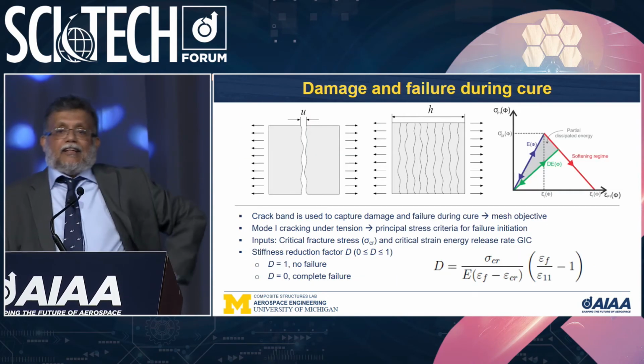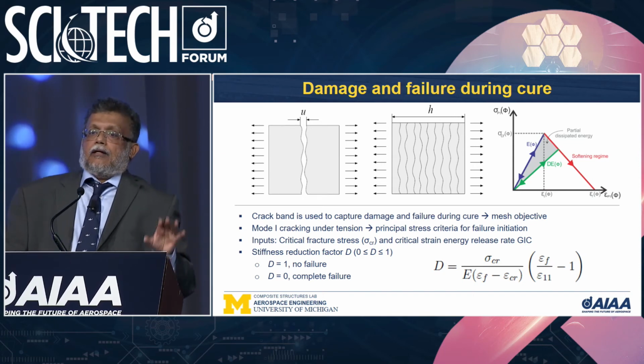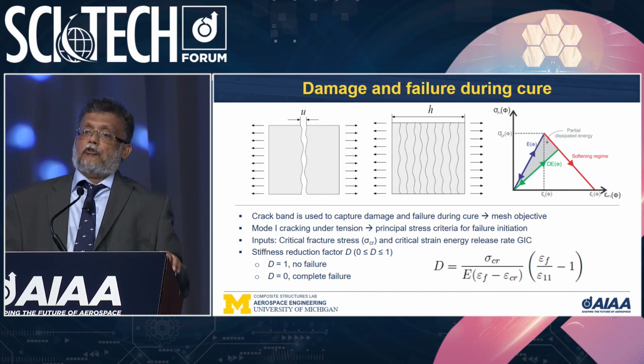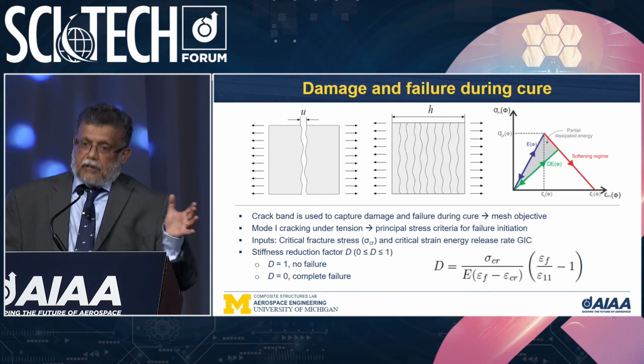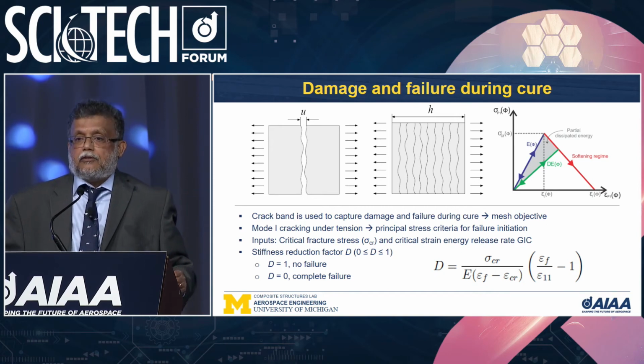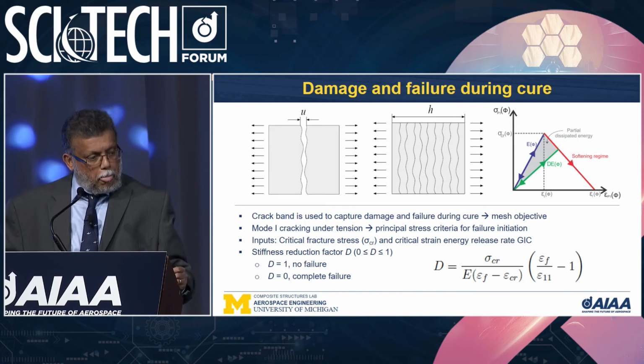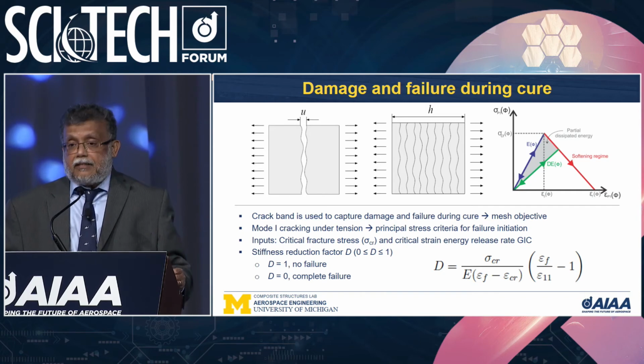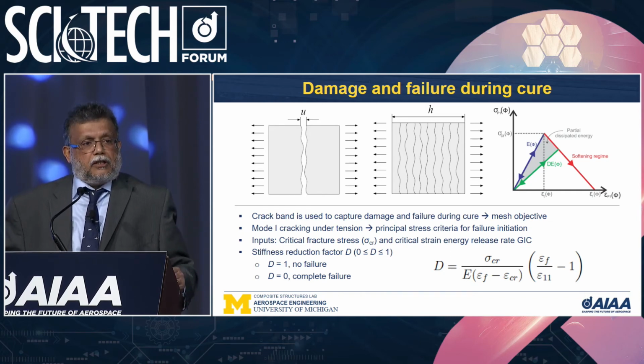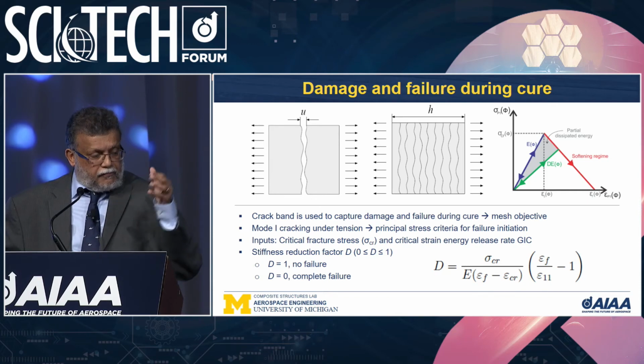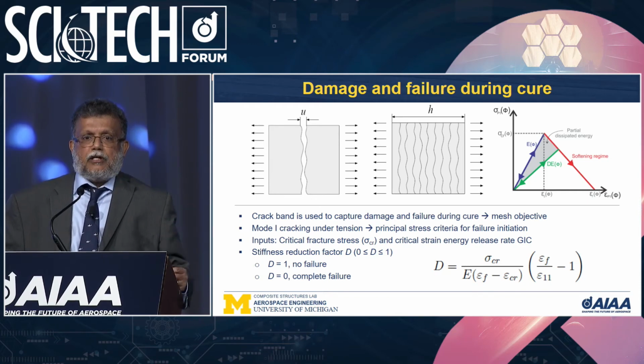Now, this problem is complicated. Damage and failure can also occur post-cure. So again, you need a crack band method to keep things mesh objective, and you need the ability to account for damage that can set in. So we've embedded our curing tool with the crack band method in order to do that.